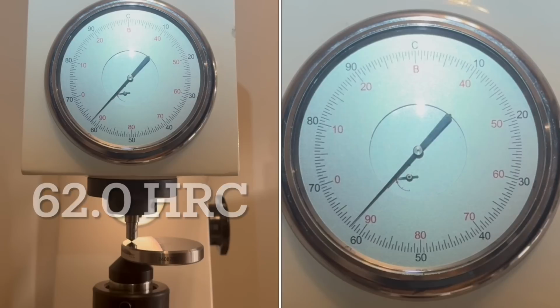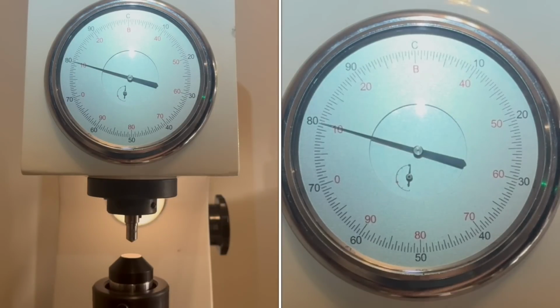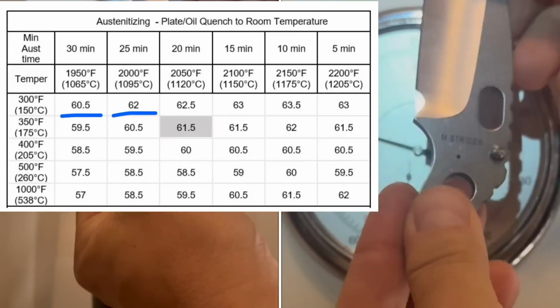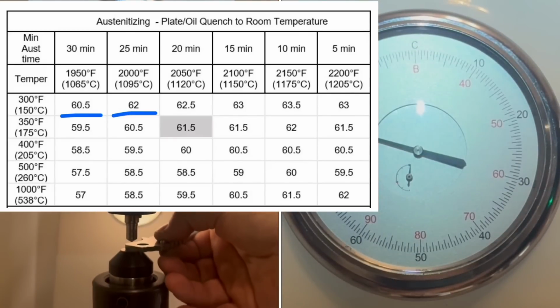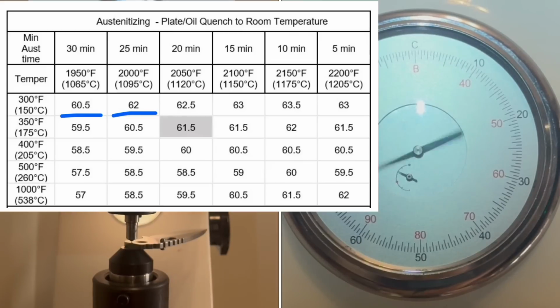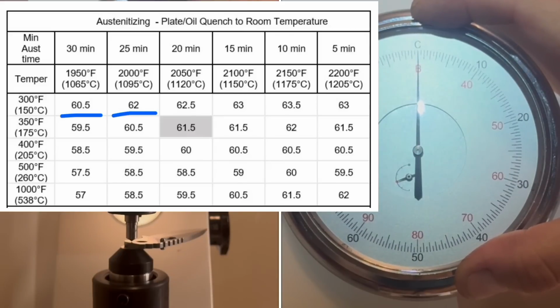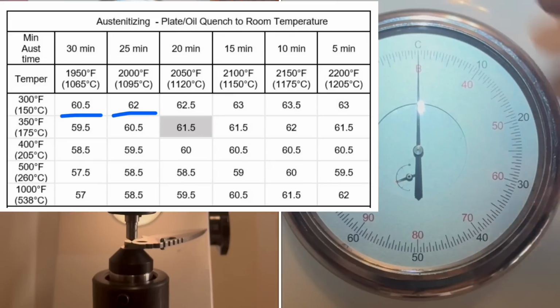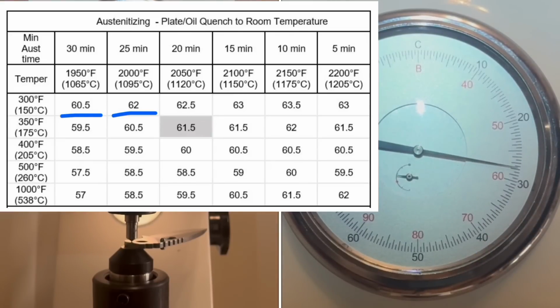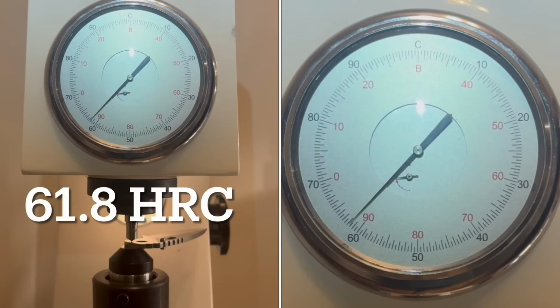62.0 HRC is actually right in calibration. Moving on, where was I? And to help our thinking process, here's the table that shows austenitizing and tempering temperatures for MagnaCut. And keep in mind, most of these fancy stainless blade steels, including MagnaCut, require double temper, meaning they heat soak them for 2 hours at what's called dwell temperature, and then bring them down at a certain rate, which adds another half an hour to an hour to the cycle. 61.8 is this one, the poke for the blade.